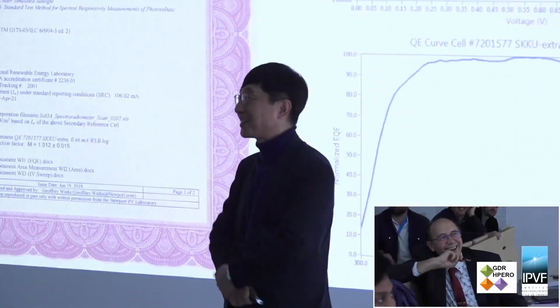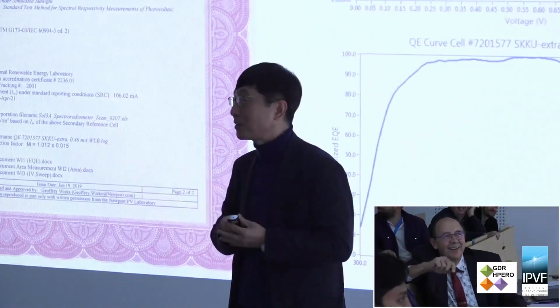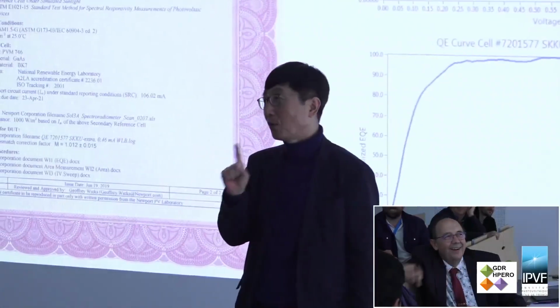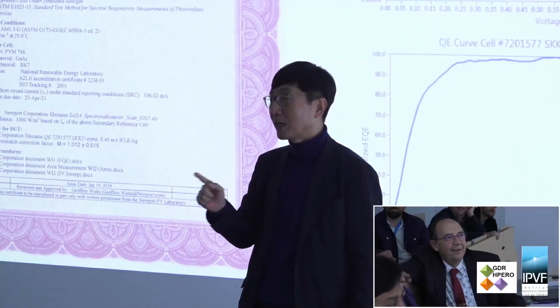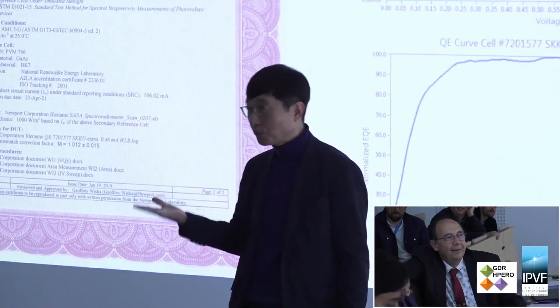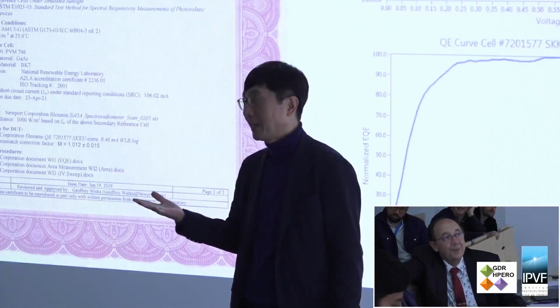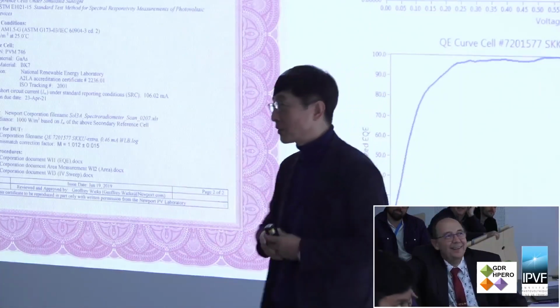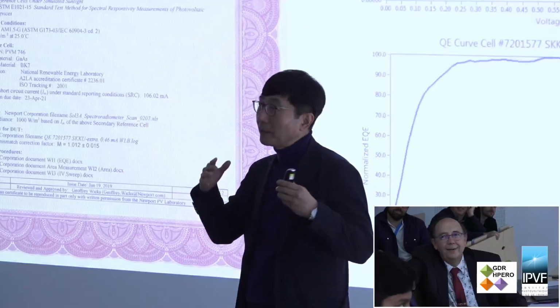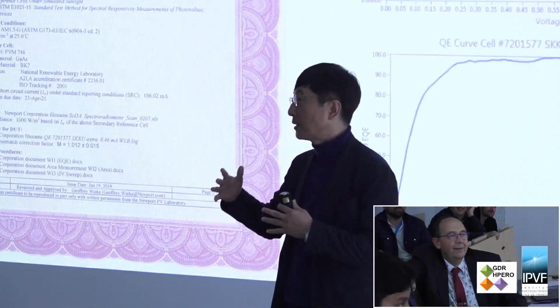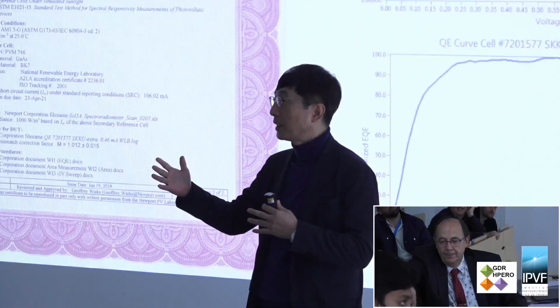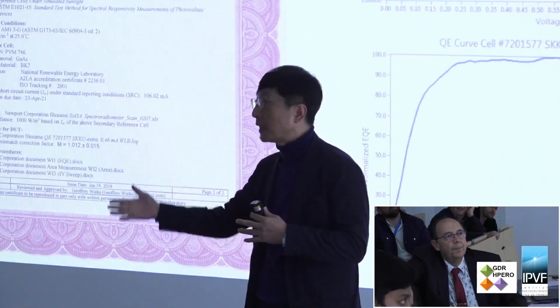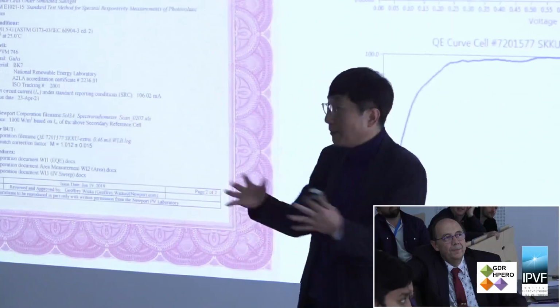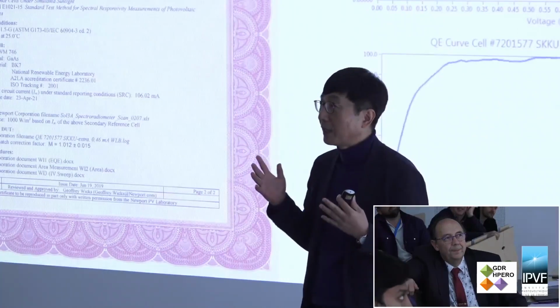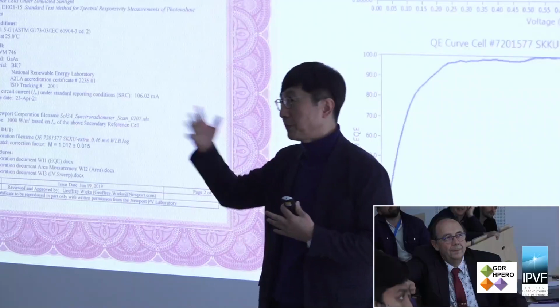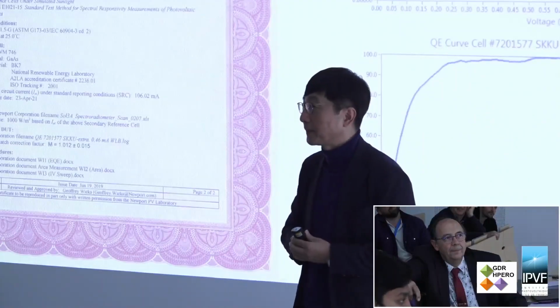This is very dangerous because we work together, and the first stage for commercializing perovskite is the tandem structure. It's good, I understand. And then the next stage is a single junction of the perovskite. After seeing the stability of the perovskite on top of silicon in a tandem structure, if the stability of the perovskite is good, we can transfer to the single junction perovskite.